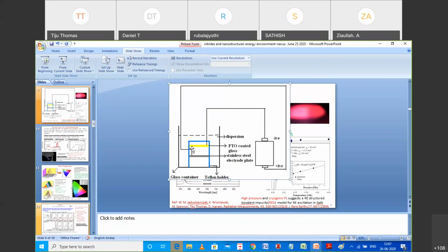And here we developed this. It's called an electrophoretic thin film deposition process, wherein you can have an electrode, you can have a working electrode, and in between you have a dispersion. So this line that you're seeing here basically marks the dispersion. This entire jig is sitting inside a colloidal dispersion, which has nanoparticles, and the nanoparticles get deposited on the surface of the working electrode. And this is how we were able to get very thin films.